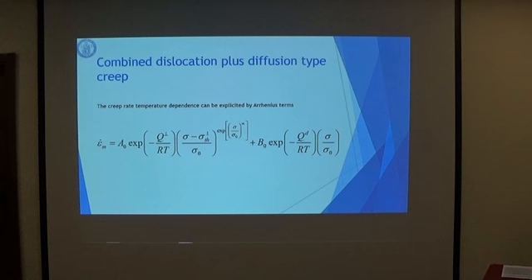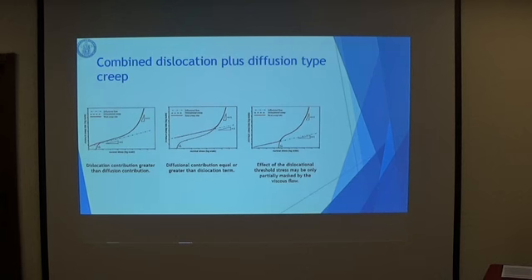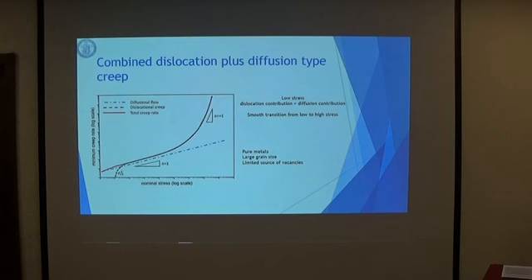So putting the equation in a more friendly way and making explicit the dependence on the temperature and on the activation energies for both the dislocational contribution and the diffusional contribution, there are three situations which can be highlighted. The first one: we have the double log plot of nominal stress and minimum creep rate. In red, there is the total creep rate.